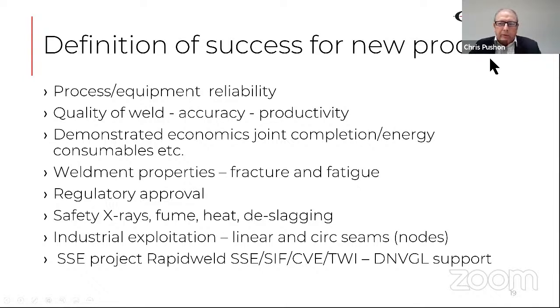What we also found was that the energy consumption of the process is significantly less than alternative multi-pass arc welding processes, particularly by the elimination of preheat. That's a big bonus. We had to show that weld properties were acceptable in terms of fracture and fatigue. And the key to all of these weld process introductions is convincing the regulator that they can put it in their standard, their specification, and say this process is fit for service and adequate.